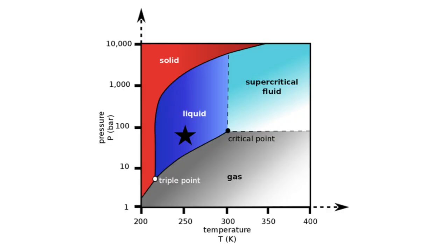Instead, what has to happen is the alcohol in the pores has to be replaced with liquid carbon dioxide, which is heated and pressurized to what's called the critical point, in which the fluid has properties of both liquid and gas, so that it can then be depressurized and take on the properties of a gas. And this is a very expensive process because it has to happen in conditions similar to a pressure cooker, which is very energy intensive and can only happen at very small scales. New innovations are taking huge steps forward to creating aerogel in ambient conditions, so room temperature and atmospheric pressure. So we can create aerogel at bigger scales and also demand less energy.